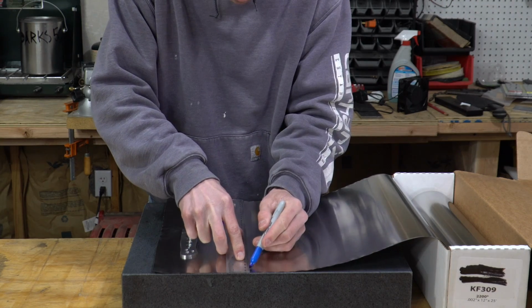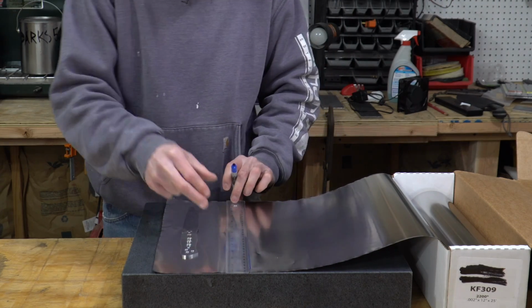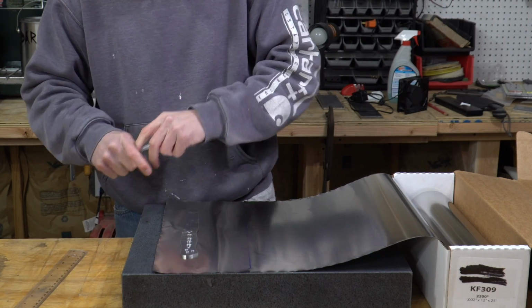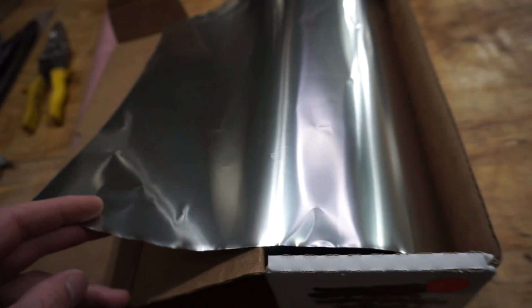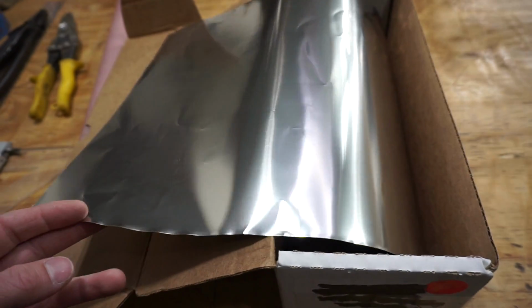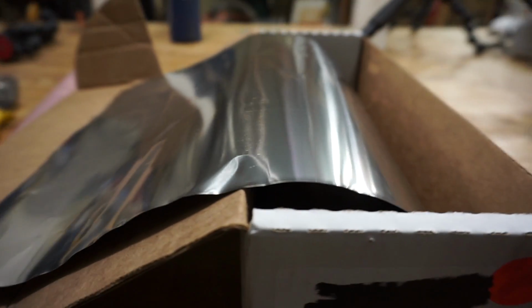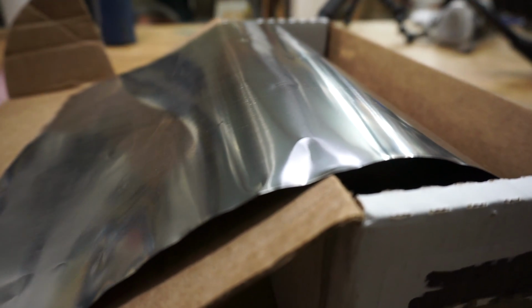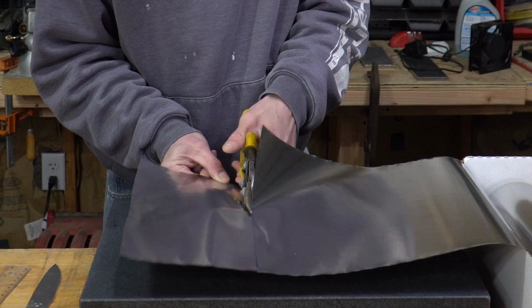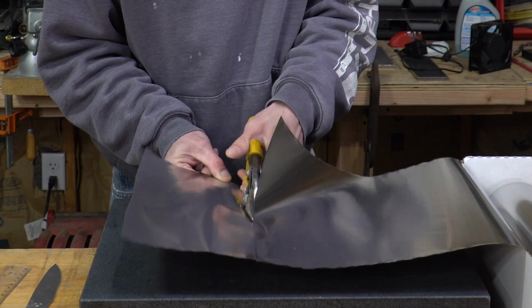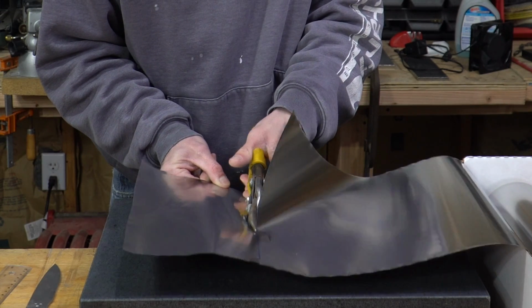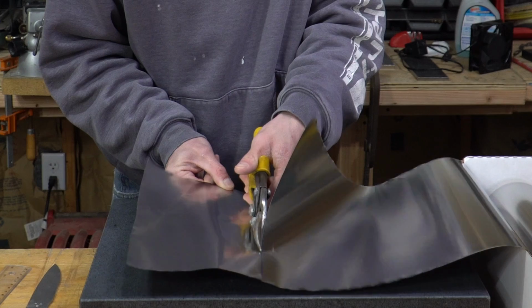So making this foil packet is relatively simple. We're going to start with some stainless steel foil, which is not aluminum foil, by the way, and it's not flashing that you get from Home Depot. Those two things will melt inside of your oven or forge. You can get the stainless steel foil at just about any of your major knife making supply dealers. It's relatively easy to find. This stuff is rated to 2200 degrees. It's sort of expensive, so use it sparingly.